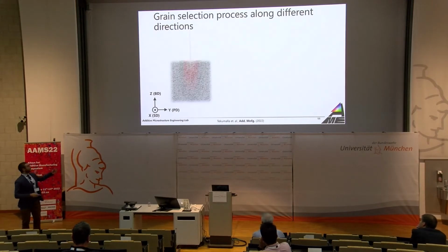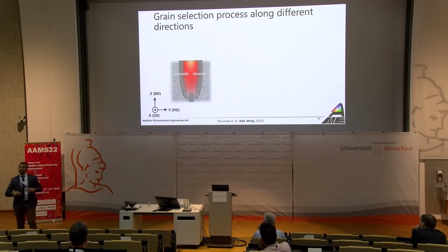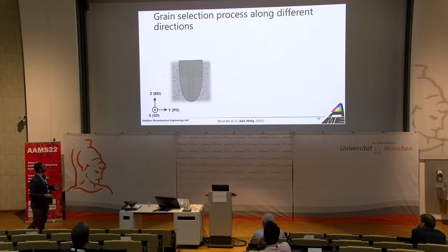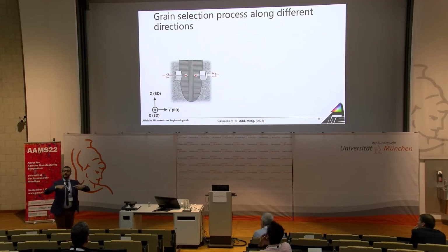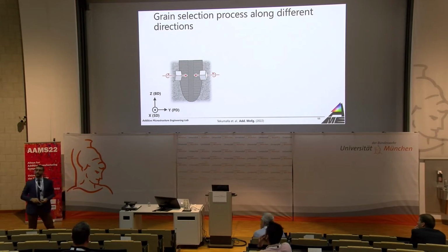In this case, we're drilling very deep keyhole melt pools. Because of the large depth of these melt pools, the thermal gradients are nearly perpendicular to the build direction. So the cells or dendrites are growing within the layer. And once everything is solid, you'll have the same fiber texture I mentioned before, but this time, as I said, along the perpendicular direction.